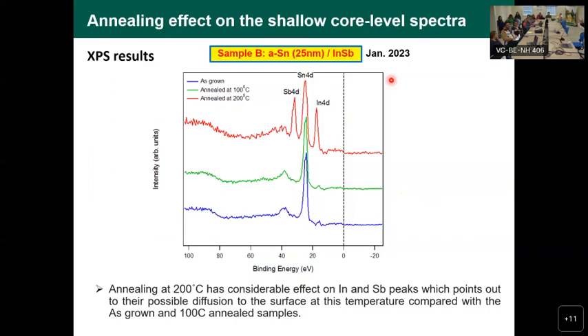Because they have their own calculations. 1 minute leads to 1 nanometer thickness, okay? So they just form the layers, any thickness we want. And actually changing the thickness changes the physics. So this is still under investigation. So what we did here, just to show you an example, we studied the as-grown sample as it is. We annealed it at 100 degrees Celsius and 200 degrees Celsius.